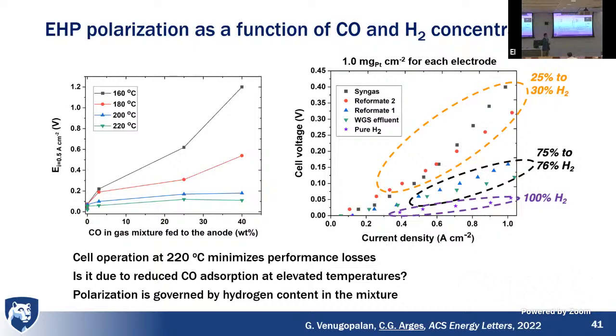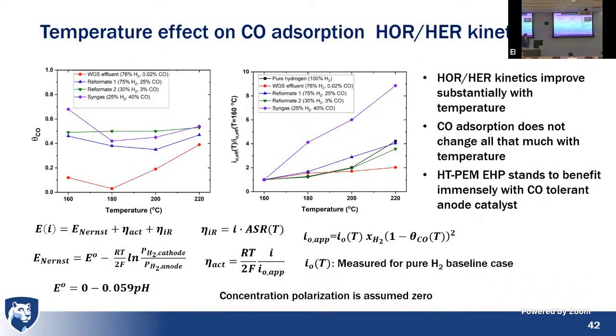But then if we look at the hydrogen content, we saw here that our polarization was also a function of how much hydrogen was in the gas feed. So we actually wanted to look at this a little bit in further detail. And we did this current distribution model again. And I had talked to people who do DFT simulations, and they didn't think CO adsorption on platinum would change all that much with temperature.